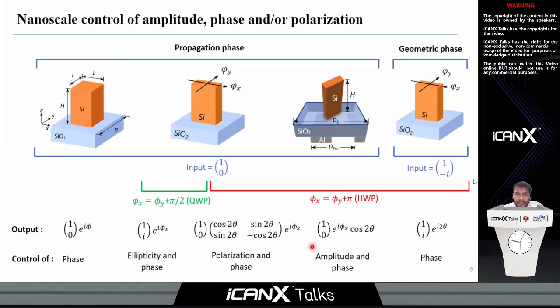And these are propagation phase-based approaches, but there's another approach which is referred to as geometric phase or PB phase, where again you design the nanopillar to act as a half-wave plate, but instead of shining linearly polarized light, you shine circularly polarized light, and what you get out is light of opposite handedness with a phase shift given by the rotation of the nanopillar, not by its size. In terms of fabrication, this is more forgiving because you're only trying to make nanopillars of the same size and rotating them by different amounts, whereas here you have to make nanopillars of different sizes. But really what this shows is this very simple approach of using very simple geometries to control the phase, polarization, or amplitude of light going through it at the nanoscale.